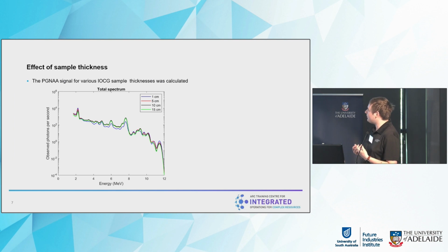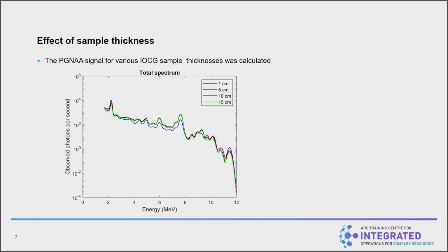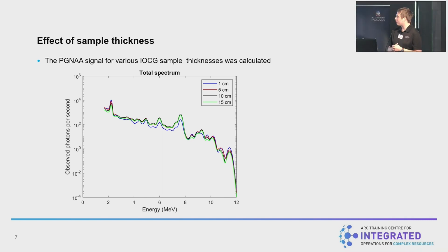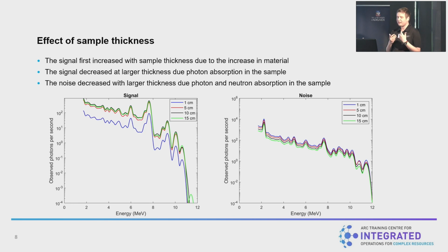So we can also use the simulation to investigate the effect of sample thickness. While the same elemental balance is present, the level of thickness can affect the response. Here we can see the energy spectrum of the recorded photons, with characteristic peaks corresponding to both the sample and the components of the sensor. And we can see that for different sample thicknesses for the iron ore copper gold material, there are complex differences in the spectrum. The simulation can be used to help interrogate this and understand what is going on, as it's possible to separate just the signal from the background noise.